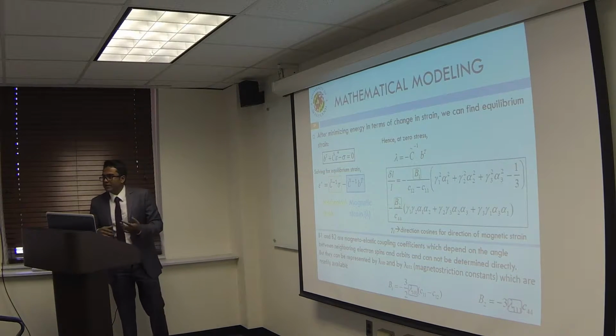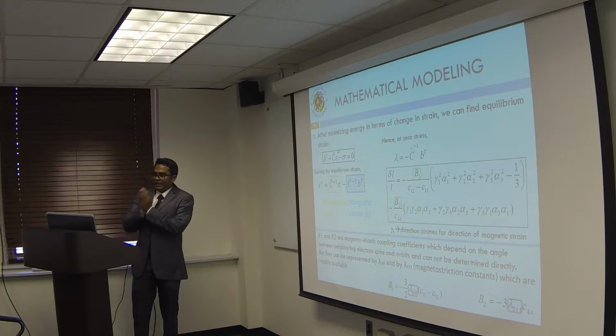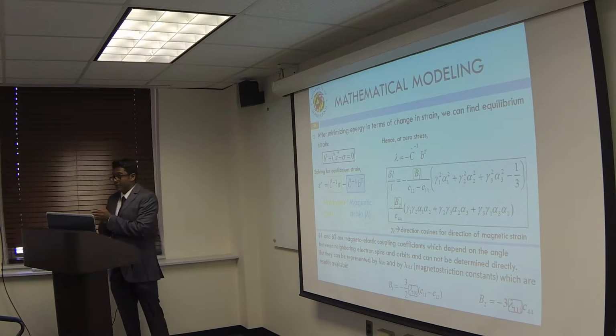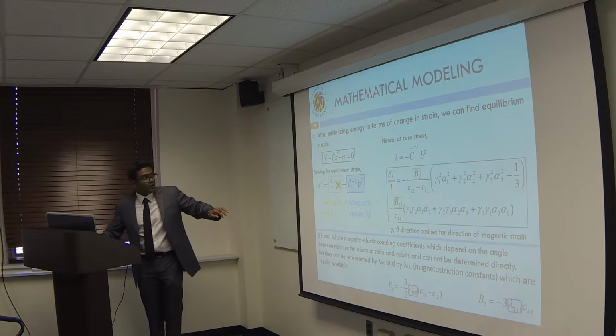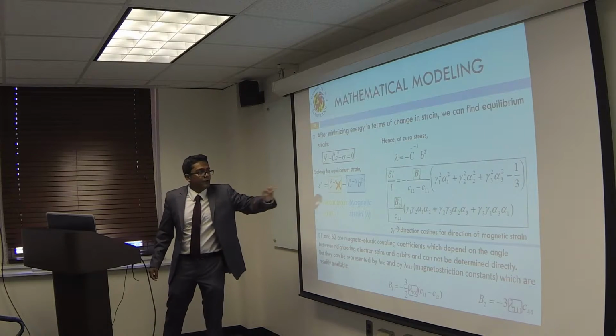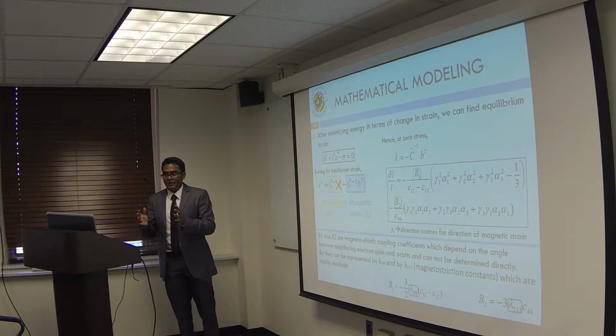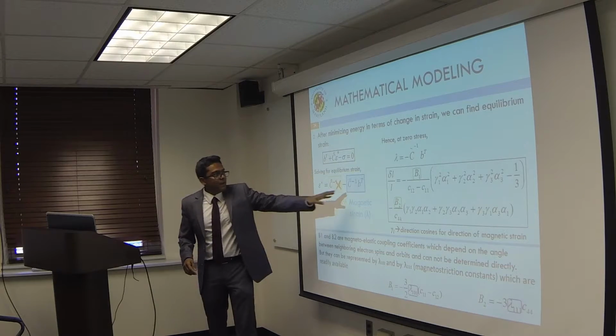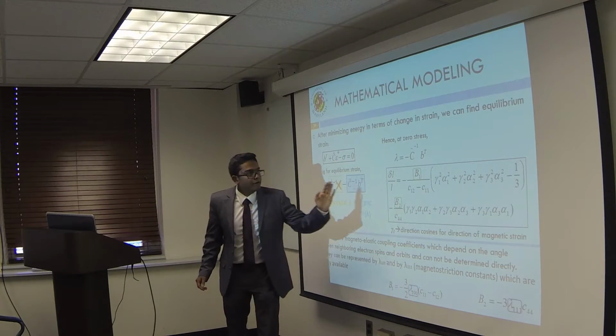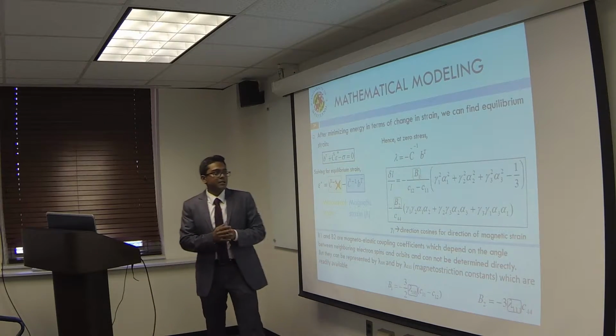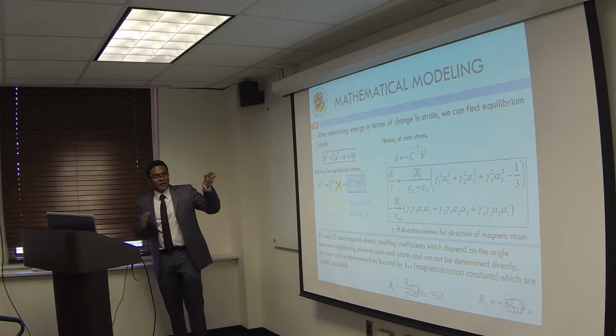There's a mechanical component and a magnetic component. And since we're going to be discussing the effect of auxeticity only under applied magnetic fields, I'm going to get rid of the mechanical strain component, and I'm going to talk about just the magnetic strain or the magnetostriction. And when I expand for the magnetostrictive strain, I find that I end up with an equation that looks like that. But here's where the trouble is.